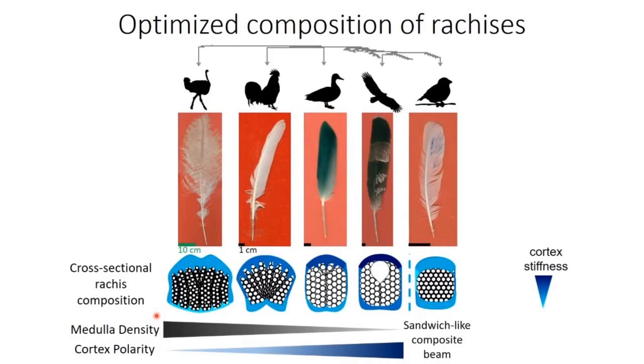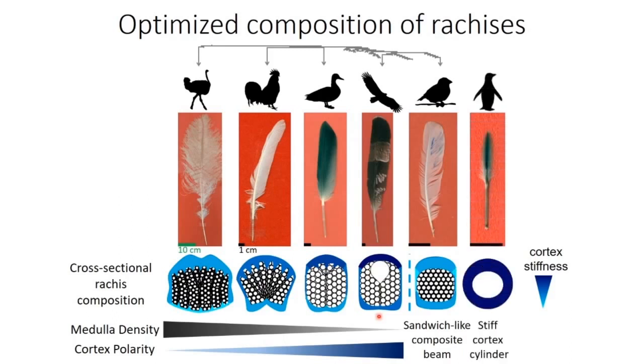We discovered that the rachis is integrated quite differently in nature. Combining the Q-morph analysis of medulla with the geometrical and material characteristics of cortex, we found that the rachis composite is integrated ingeniously with a simple and light medulla core with a polarized cortex reinforcement in the feather of good flyers. The water-diving penguin even shows extreme reinforcement of the rachis: the cortex-only configuration. The variation of Q-morph patterns suggests an evolution of the keratin allocation strategy in the feather rachis to overcome ecological challenges.